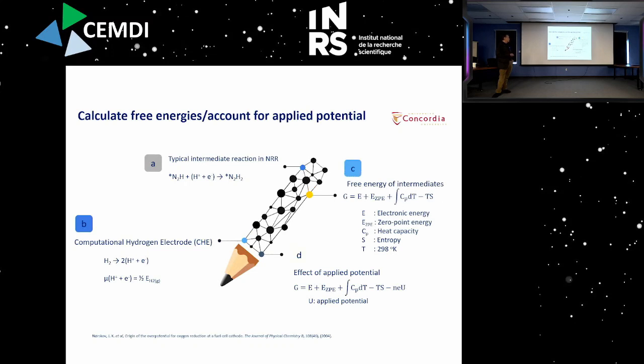And so this is a slide that shows how we calculate the free energy profiles and account for the applied potential. We looked at the typical intermediates. We're going to use the computational hydrogen electrode, which is a shortcut where anywhere we have the proton and the electron, we take the chemical potential for this entity as half the free energy of the hydrogen molecule. So we can evaluate the free energy of the intermediate by standard procedures, and we take into account the effect of the applied potential by just adding a term on top of our DFT calculation, which up to this point ignores the effect of the electrode potential, something I'll get back to towards the end.